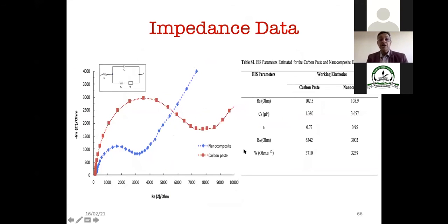We also obtained the impedance data to make the equivalent circuit. We have done the simulation of this, and this is the Nyquist plot that we obtained. With that, we try to estimate the values. These are the observed data, and this is the simulated data. For the equivalent circuit, RS is the solution resistance, RCT is the charge transfer resistance, C is the capacitance, and this is the Warburg resistance.